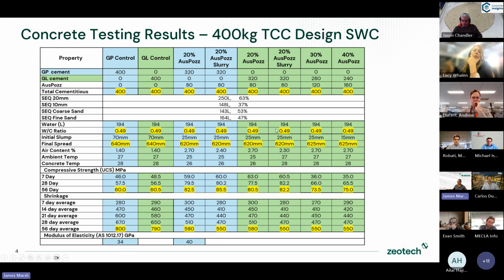Metakaolin is renowned for having a higher water demand normally, and that's usually because it's made too fine for concrete. It's usually made for other applications, but used in concrete, it means the water demand's high, and that does give some problems. Well, we've designed our AusPozz with the optimum particle size, which has a D50 of about 20 microns, which means the water demand is actually not that bad. So it doesn't need a lot more water. In fact, in this case, we didn't need any more water at all. We kept that at 0.49. The test work we did here, we kept the water the same. Then we measured the initial slump.